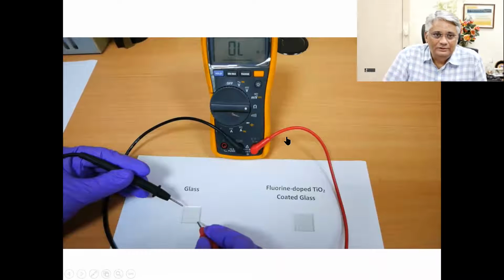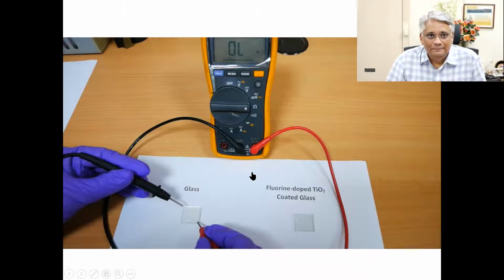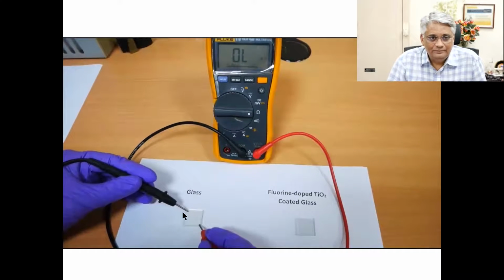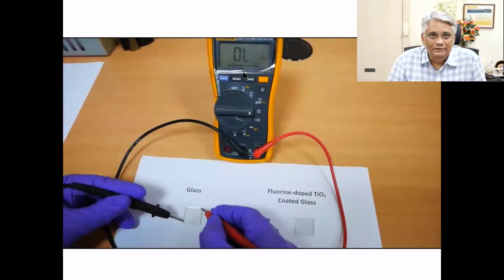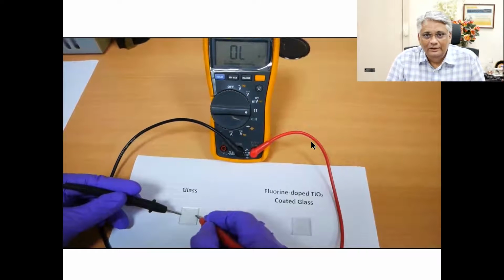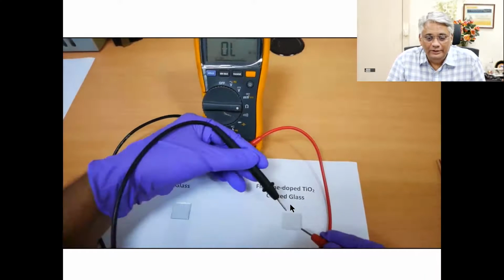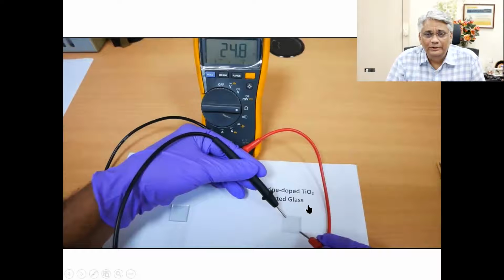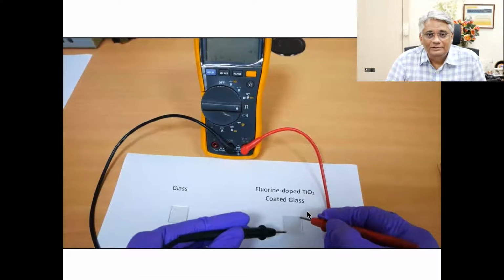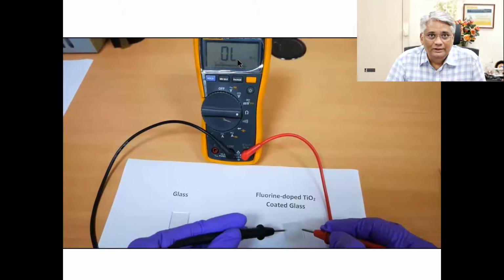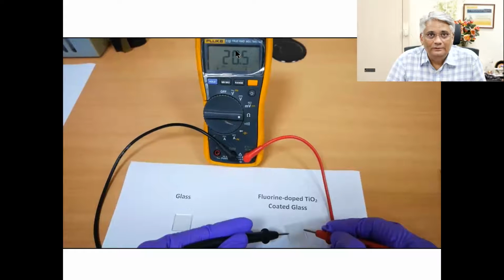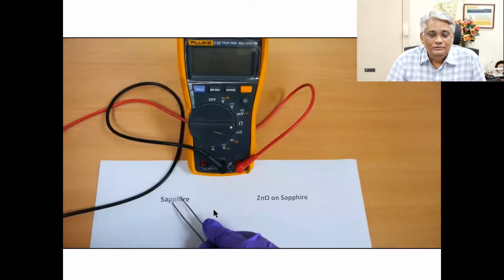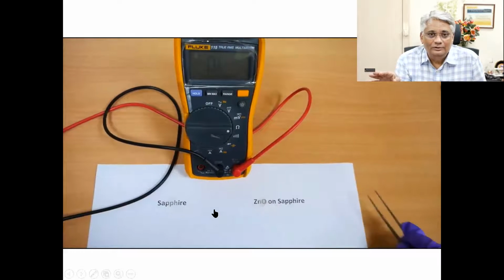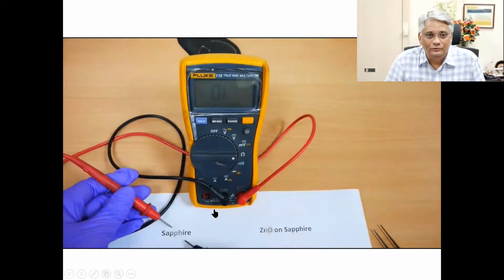Look at this small video that we have created for you to appreciate how conductivity and transparency both coexist. Okay. Now, this is glass, of course, right? And you see the meter here, it shows overload. Okay. Glass is non-conductive. And this is fluorine-doped TiO2 coated on glass. Fluorine-doped TiO2, titanium dioxide, has applications as TCO, transparent conducting oxide. You see that it shows about 20.5 ohms. Okay, so from glass to fluorine-doped TiO2, certainly there is a huge change in conductivity.